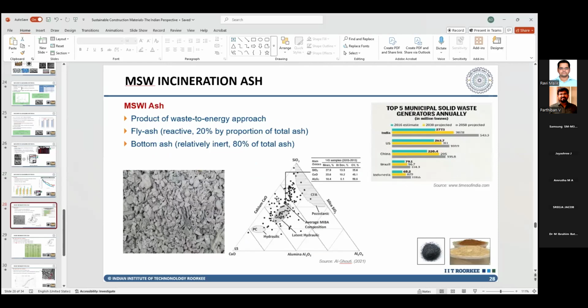India's trend, particularly in the major cities where this incineration will actually work. First of all, incineration is not something that can be applied to every municipality. A tier 3 city, definitely it will not work, it will not be viable. But for a tier 1 or even a tier 1.5, tier 2 city, they generate 6 to 7,000 tons of waste every day. Out of that, at least 50% is dry waste. So their waste to energy plant works well, but still they become economically unviable because the electricity that they are generating, they sell at 7 to 8 rupees approximately, whereas from solar or from thermal you get it at much lower cost.